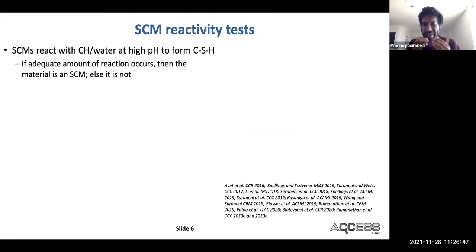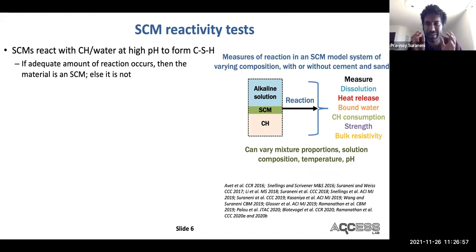Now, I want to take a step back here and discuss broadly what the idea of most of these reactivity tests is. All of them essentially function on the principle that you take some sort of a system where you have SCM, calcium hydroxide, and an alkaline solution. You let them react and you measure various parameters. Could be dissolution, could be heat release, bound water, etc. All of them are measures of reactivity. You can change the system tremendously. You can add cement, you can add sand, you can change the composition, temperature, pH. It kind of doesn't matter to a certain extent. The basic principle is all the same. If an adequate amount of reaction occurs, then the material is an SCM, else it is not.